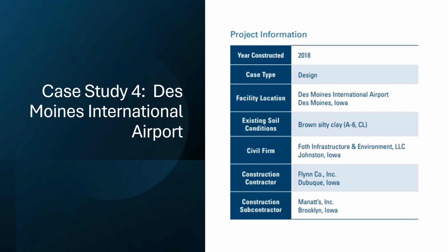The tests conducted were Atterberg limits, grain size analysis, and Proctor tests on the samples at 3 different dosage rates. Each cement dosage rate yielded an increase in strength of approximately 100 to 300% over the untreated soil. Based on the results of the study, the project utilized a cement dosage rate of 4%, which equates to approximately 38 pounds per square yard of cement.